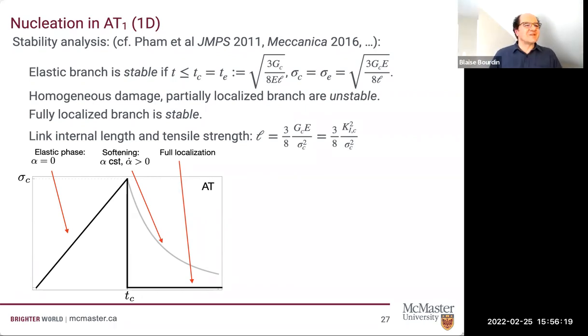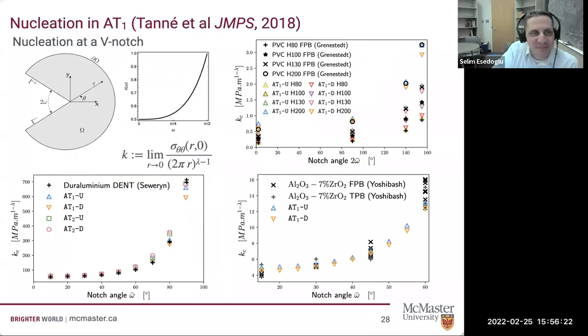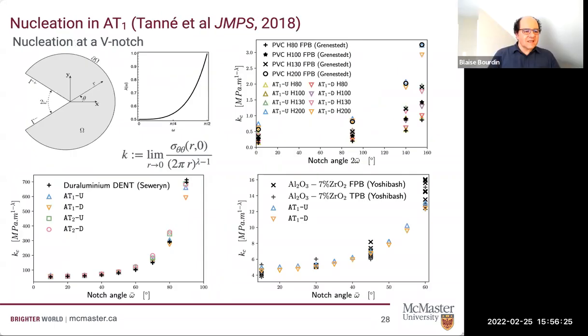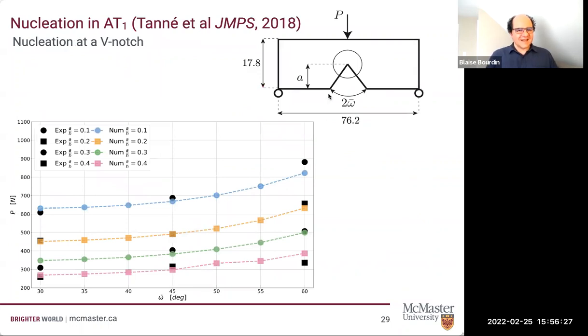And I'll just show one picture, or maybe two. Okay, let me see. Yeah, I'll just wrap it up with this. So this is a three-point bending problem for a domain that has a notch, for various values of the notch angle and the notch depth. None of these cases can be accounted for in the Griffith theory. The black dots are physical experiments, for various values of the notch angle and notch depth.